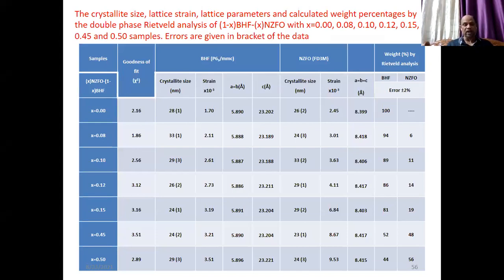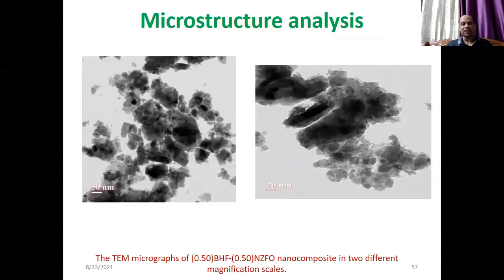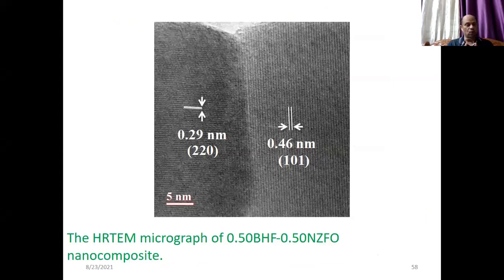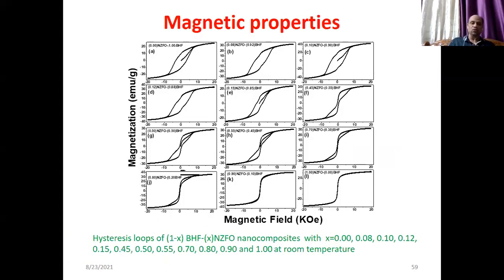So once you get it, then we go for the TEM picture and find out if they are really diffusing and sitting. Although the question will come that no doubt there will also be the particles of the BHF, but we try to find out whether they are really forming it or not. They are coming close to each other, and we found that the different phases are coming close to each other and without interacting, they are showing their structure. So after that, you go for the hysteresis loop measurement.